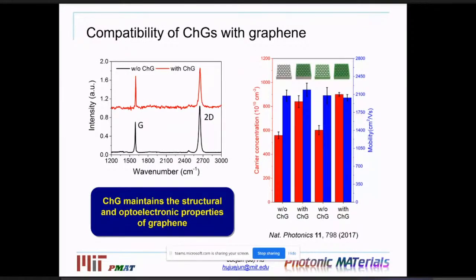Now, this is where chalcogenides come in. Like I mentioned, because they can be processed at room temperature, this very low thermal budget minimizes any kind of structural disruption to the underlying 2D material. So in the case of graphene here, we see that the deposition of chalcogenide does not disrupt the underlying graphene substrate. They also maintain the high mobility in these graphene materials without changing any of the inherent structural properties.